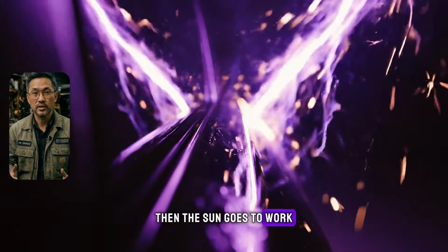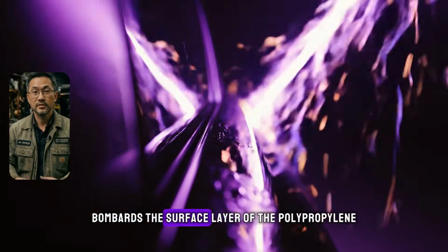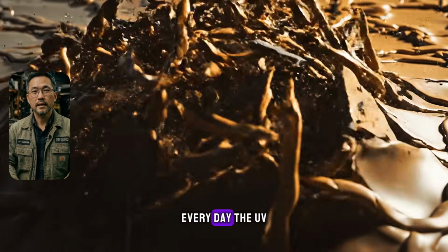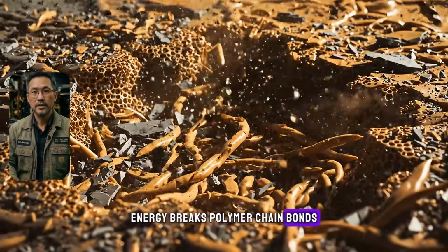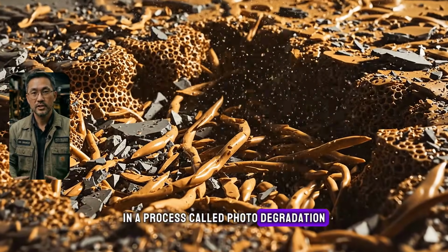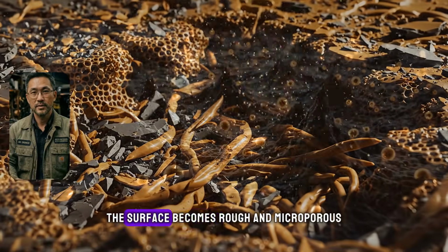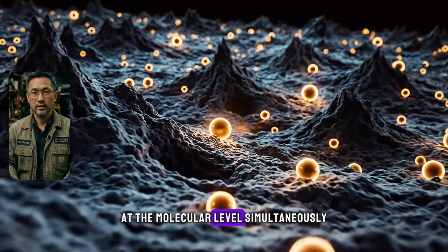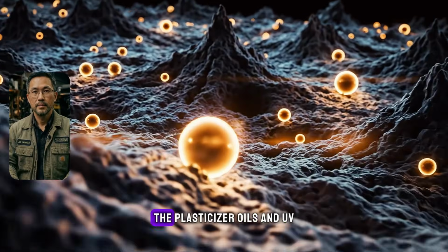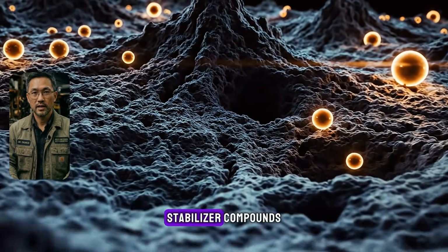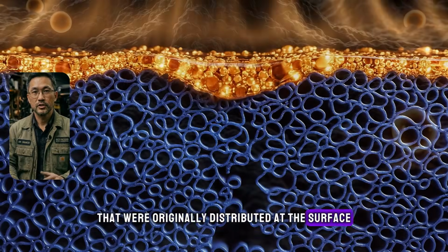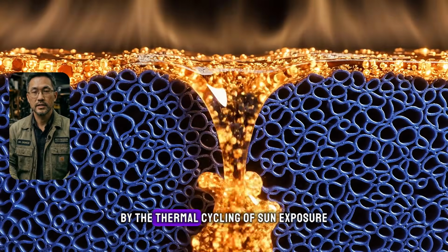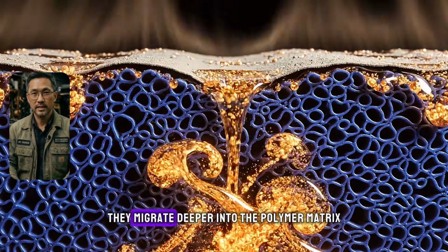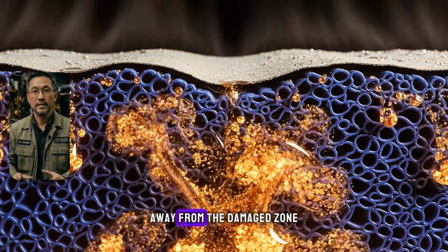Then the sun goes to work. Ultraviolet radiation bombards the surface layer of the polypropylene every day. The UV energy breaks polymer chain bonds in a process called photo-degradation. As the chains break, the surface becomes rough and microporous at the molecular level. Simultaneously, the plasticizer oils and UV stabilizer compounds that were originally distributed at the surface are driven inward by the thermal cycling of sun exposure. They migrate deeper into the polymer matrix, away from the damaged zone.